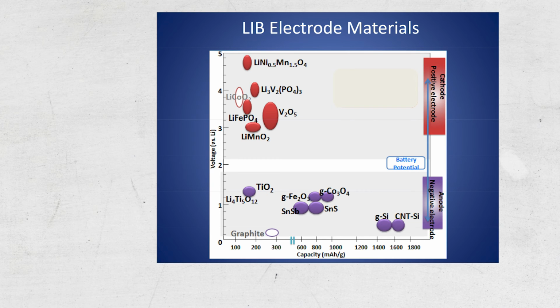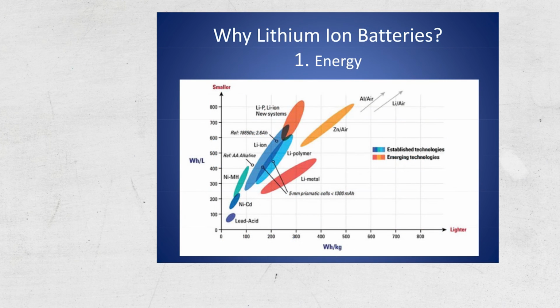So you see here that titanate, the titanium oxide, is around 1.2, 1.3 volts. And there are many other materials based on other oxides, cobalt, iron, and tin, sulfide, etc. that also provide high capacity, but the voltage is high. And now the prospective anode materials are here, the carbon nanotubes mixed with silicon, and silicon as well. So anyway, there is a huge amount of work to come up with new anode and new cathode formulations to improve the energy or power density of the batteries.